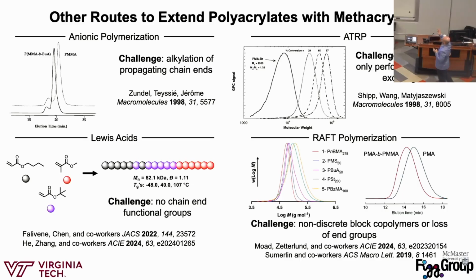You could also think about ATRP, which is just another flavor of controlled radical polymerization. Krzysztof Matyjaszewski showed this in 1998, going from polymethyl acrylate to methyl methacrylate. You can do this by synthesizing your acrylate with a bromine chain end, and then you do a halogen exchange to a chlorine, and then based off bond dissociation energies and some kinetics, you can do this flip to methyl methacrylate, but you can't go back. So you can go one way, but you cannot flip the other way. You have to do some chain end functionalizations, which usually lose the chain end anyways. And so no one's actually shown that you can make a triblock of acrylic, methacrylic, acrylic using ATRP, because once you flip it, it's just harder to work with.